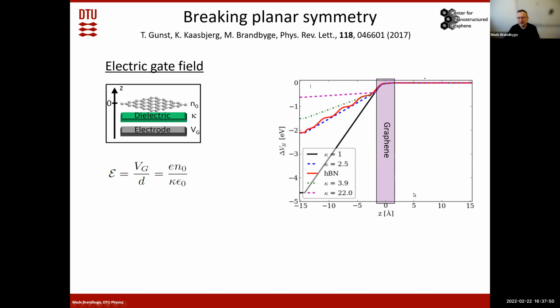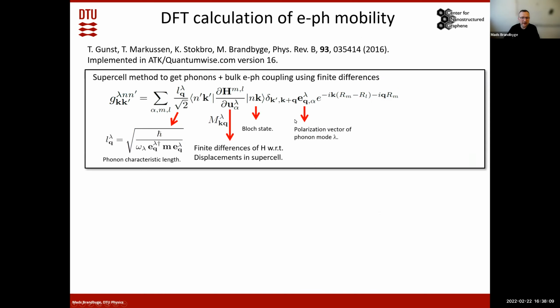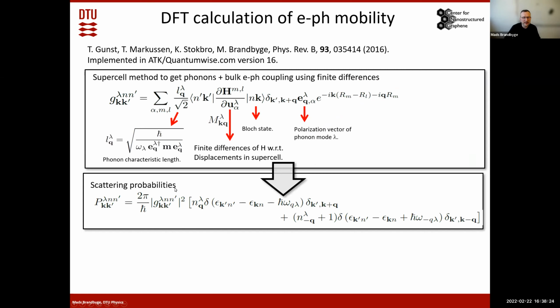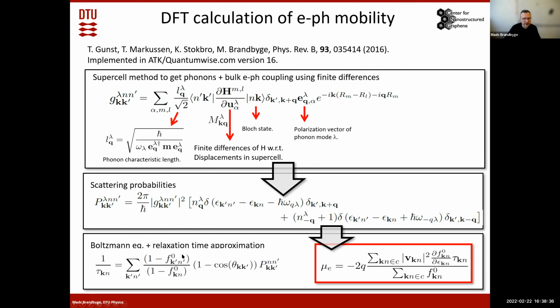So what you see here is a graphene device, and you have a gate here and different dielectrics in between, like this. And here you see the Hartree potential of the electrons, and you can see how the gate is breaking the left-right symmetry of the graphene. So we have implemented the calculations of electron-phonon coupling in this QuantumATK software, and then we can calculate the electron-phonon couplings and all the phonons, and from that we can calculate scattering probabilities between the different electron states in the graphene, and if we put it into the Boltzmann equation and the relaxation time approximation, we can calculate mobility.